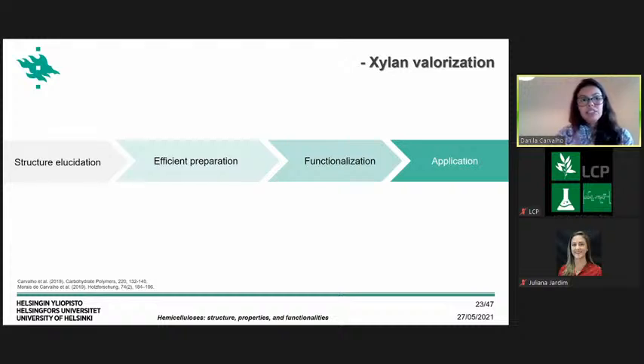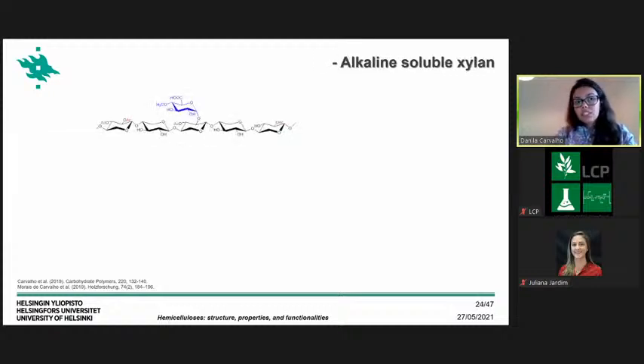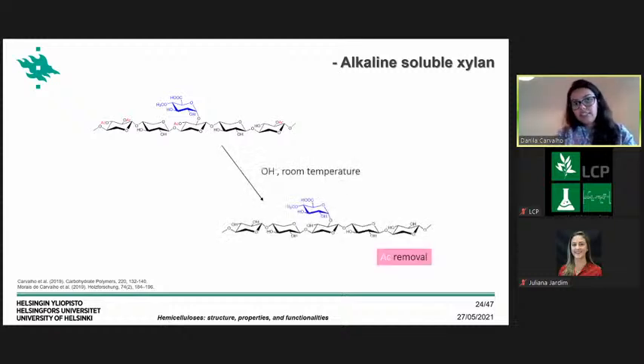And since the structure was already elucidated by us or by other researchers before us for those biomasses, what we started to do in this project was an efficient preparation of the xylan samples. As I told you, the dimethyl sulfoxide is not good in terms of generating a high amount of xylan. Then we started to use a different strategy. And this strategy was using an alkaline condition instead. The alkaline condition can give very high yield, but what happens during the treatment is some chemical modification of the structure of the xylan. In this case, it's the removal of the acetyl groups.